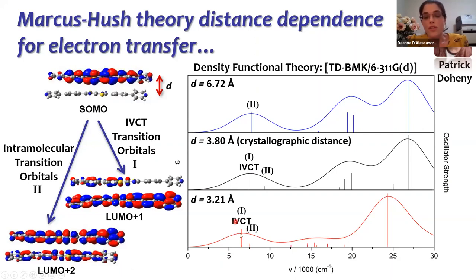If we squash the two ligands further together, we retain these two transitions. But if we pull them further apart, we lose this intervalence charge transfer transition because they're now too far apart for the electron transfer to occur.